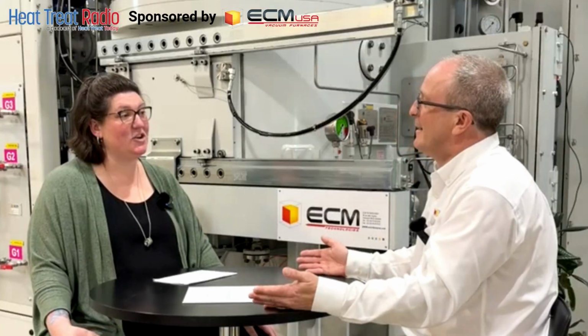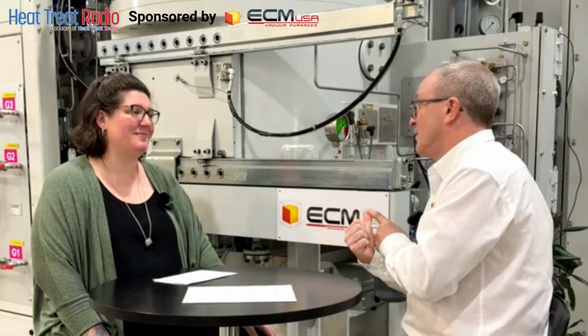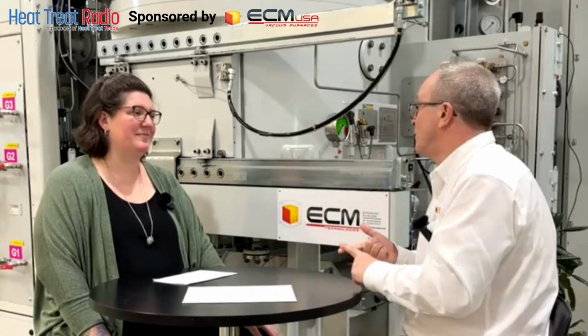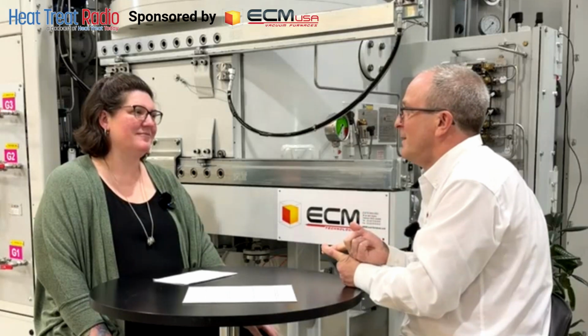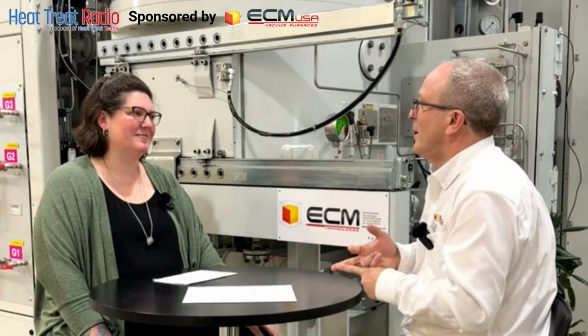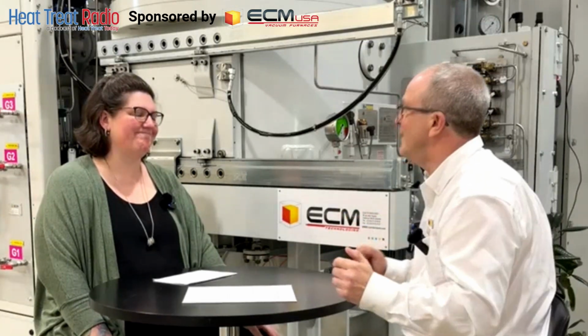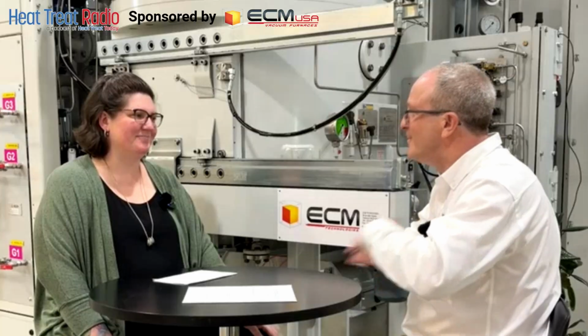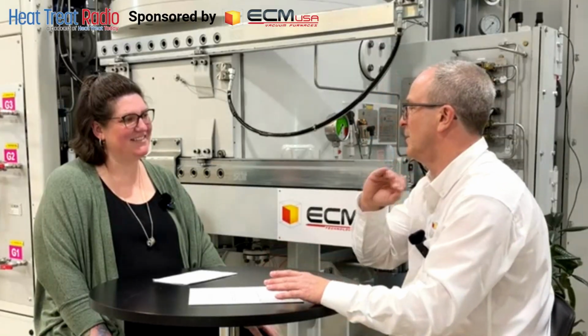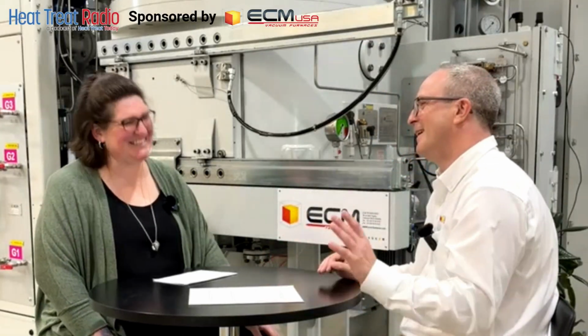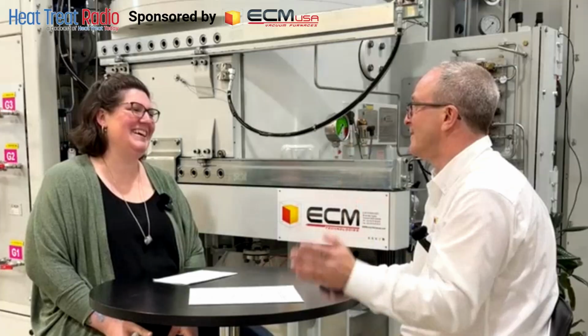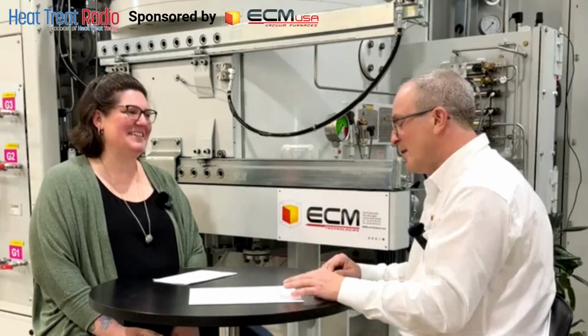Makes sense. Start there. Heating time was not long enough. Gas flow was not long enough. And I found that they were not working at the right pressure in the furnace. So failure. I said, change that. No news, good news, usually. If the customer doesn't call you, it's because everything works. So it's the beauty of this furnace. So the repeatability, it's like that.